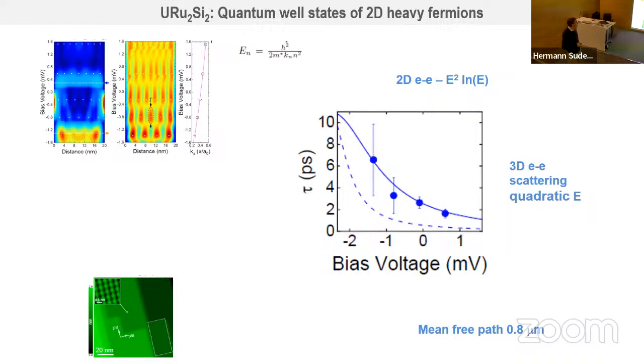And what is probably more important is that you can extract the lifetime of these states. And curiously enough, the lifetime of these states, even being heavy fermions, or because they are heavy fermions, has been renormalized to relatively high lifetimes. So you can fit this using a two-dimensional electron gas, but you have to put in interactions, and then you get something which is more or less like the energy squared, and that works out. From this you can also extract the mean free path, and you get something more or less compatible with the bulk mean free path.